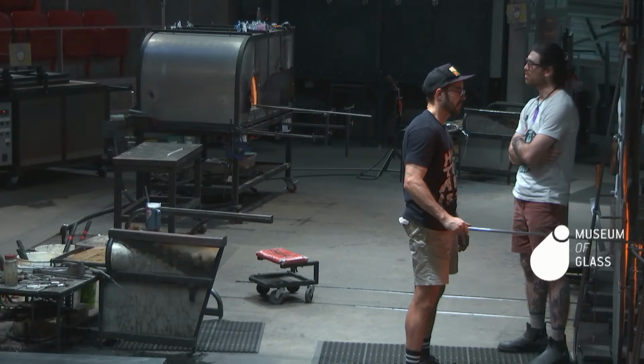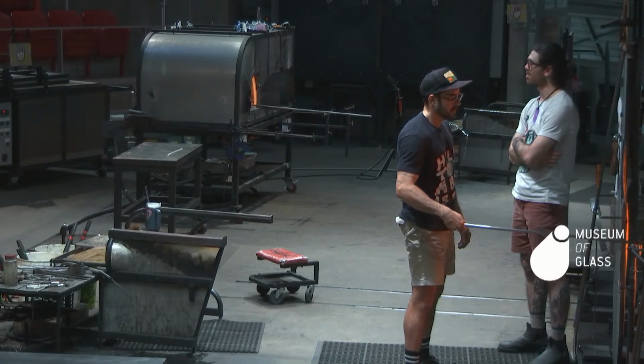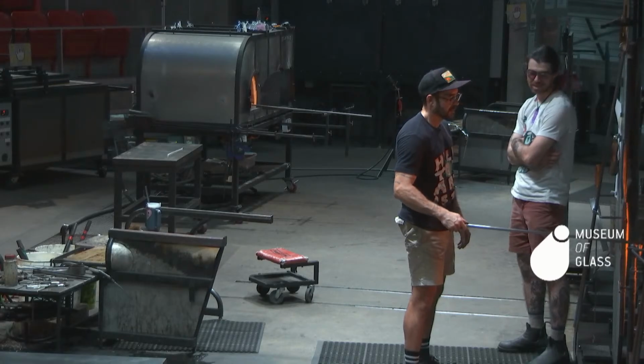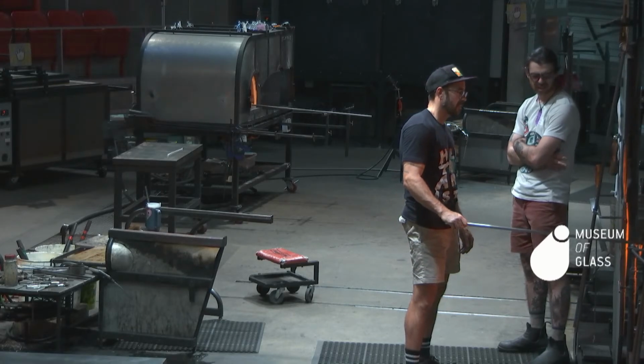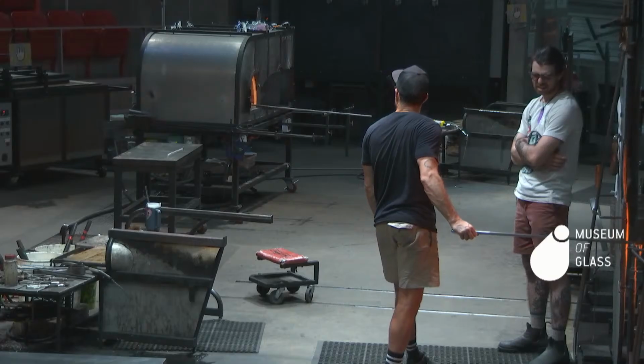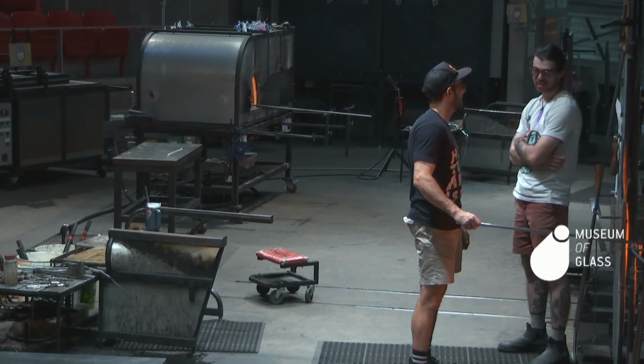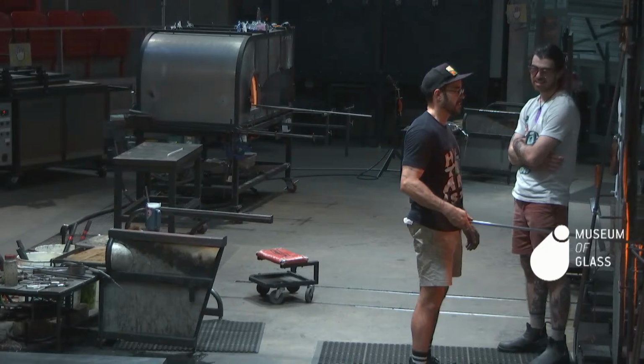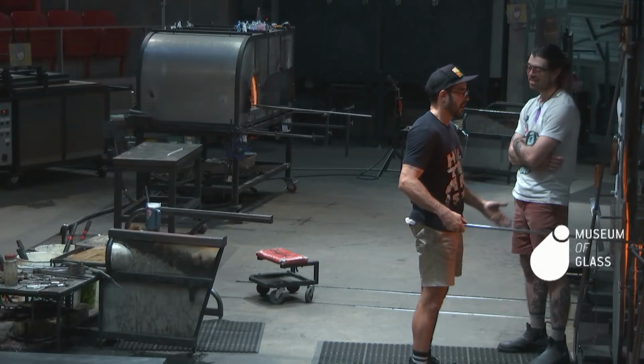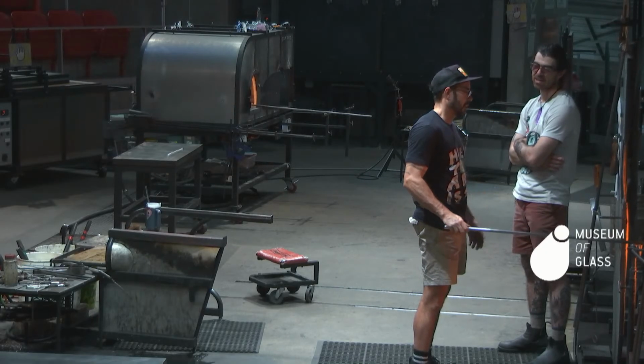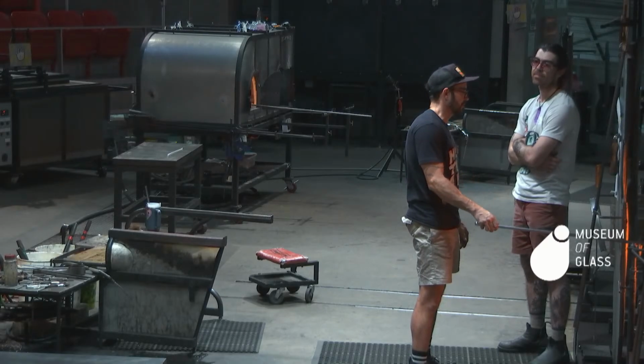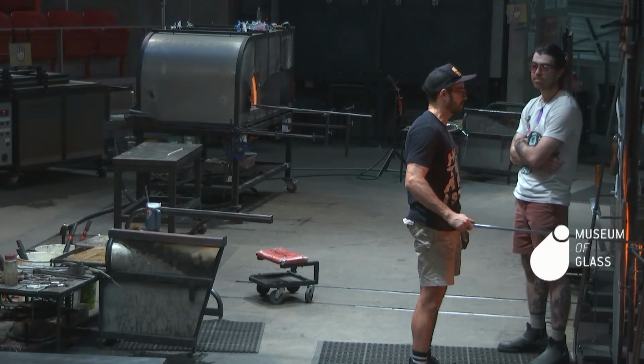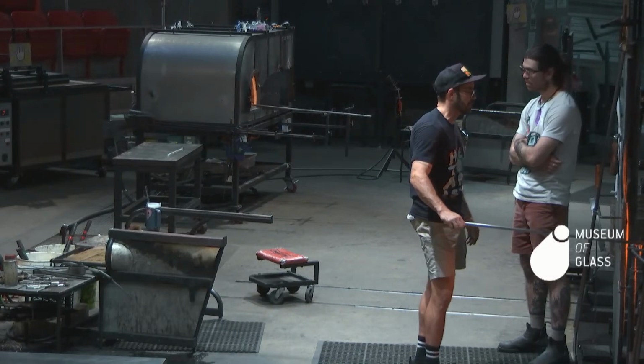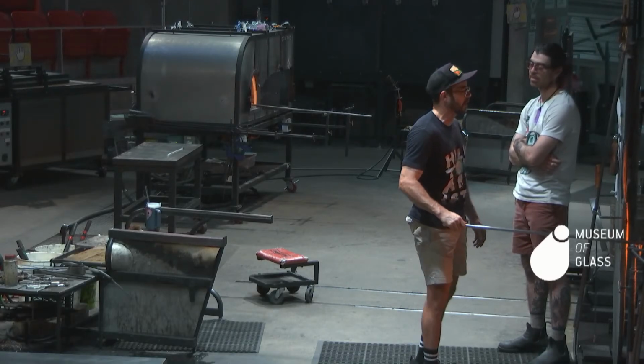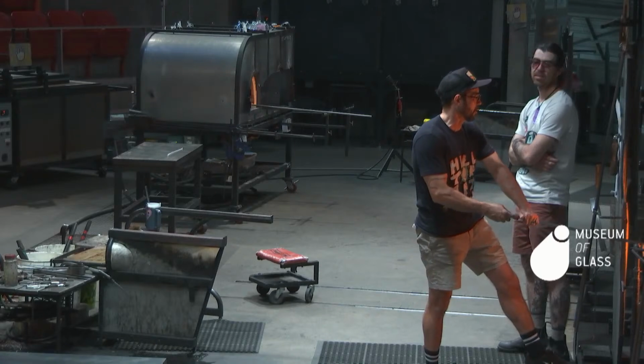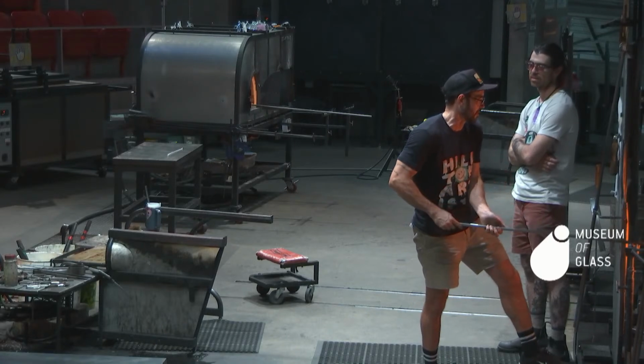Because if there was clear on it, they would have to carve into it really deep, and it would have really big grooves in it, which would translate as thick and thin spots in the glass. And that makes it really hard to blow glass if it has thicker and thinner spots, because the thinner it is, the faster it cools, and the thicker it is, the longer it stays hot. So if it has different temperatures in the piece, when you blow the bubble, it blows out in the thicker spots more than the thin spots. It makes it pretty difficult to work with. So having the color on the outside makes it less of a difference in the thick and thinness, which makes it easier to control.